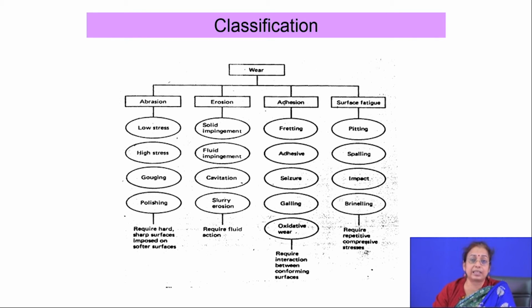At the end of the wear test, if it is erosion testing, then your media is not solid, and the kind of testing you apply is a little different. There you basically have media which is full of liquid, with solid particles dispersed in the liquid. Then you have relative movement of the component, done either by moving the liquid or by moving the component, and at regular intervals of time you measure the loss of mass because of the wear.